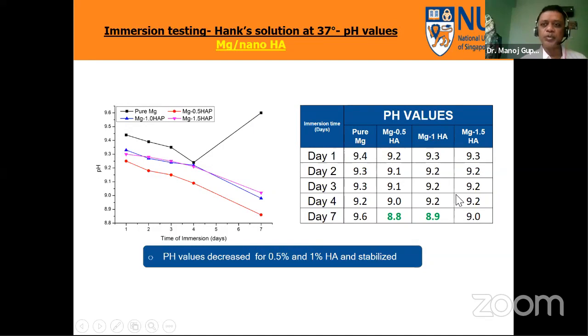Now if you look at the pH values, again similar to the corrosion rate, you will see the pH values are quite similar, but the best values, if you really want to compare, are still for 0.5 HA and 1 HA.